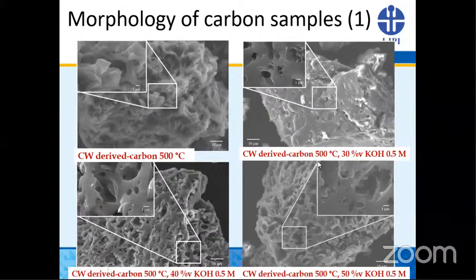Okay. So we made some variation, we made some variation regarding the volume of the solvent. This is 30% and 40% and 50%. From here, from this three variation, we can see here when we use 40% volume, the pore development is better than for other treatment.